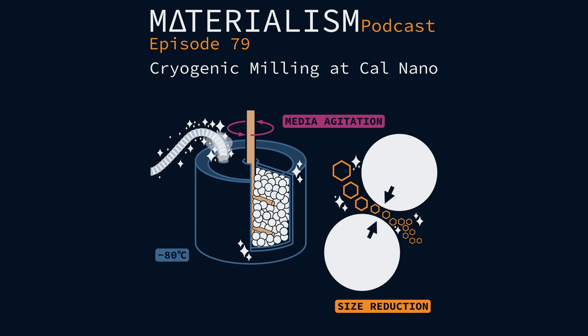I did see one way around this problem of impurities. When I was at Ceramitech, we were working on ceramics, which are pretty robust chemically, and they used steel milling media, right? Because of the steel filings, they could just do an acid wash. The ceramic was pretty much unaffected. I think we were working on a YSZ at the time. Mm-hmm. And you could dissolve away the other impurities. So I guess there are some clever ways around it. And steel is kind of a nice high-density material anyway.